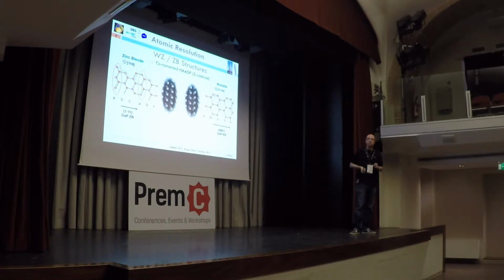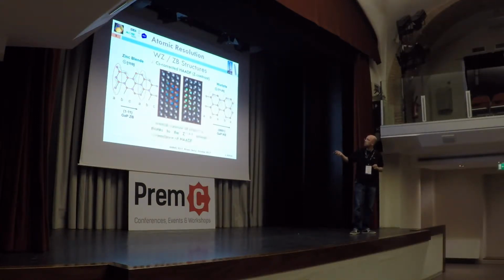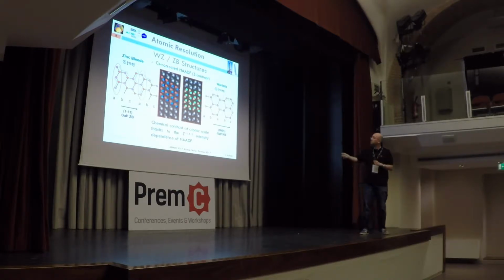So at the atomic scale, they look like this. You can see perfectly the atoms here, how they are stacking. This is the ABC stacking of the atoms, and this is the zigzag AB stacking here. So the minimum reference of the atoms here is this binary system, which we call a dumbbell. You have here the anion and the cation. So these are facing one direction, and you can see that in one direction the cation is facing on top, but in the other direction of these 111 planes, the cation is facing the other side. And here it's the same: the anion is on one side, and the cation is on the other side.